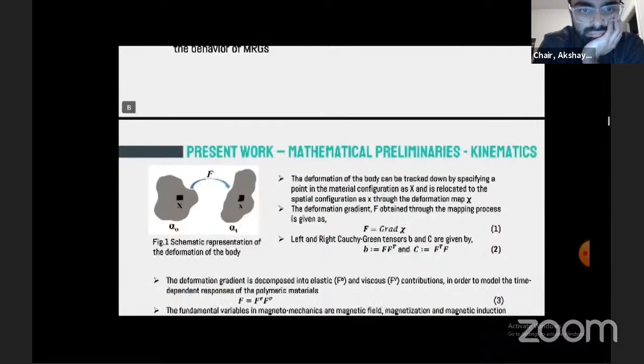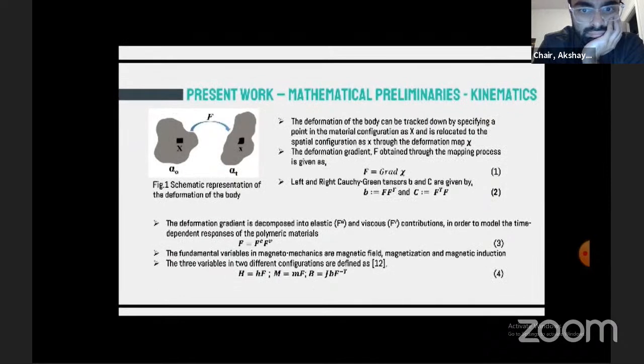The present work starts off with the mathematical preliminaries, which involve the kinematics of the magnetorheological gels. Generally, the deformation of a body can be easily tracked by specifying a point in the material configuration, which is relocated to the spatial configuration, and this can be mapped using a deformation map chi. The deformation gradient F can be obtained through this deformation map chi and is defined in equation 1. Based upon this deformation gradient, the left and right Cauchy-Green tensors are given in equation 2.